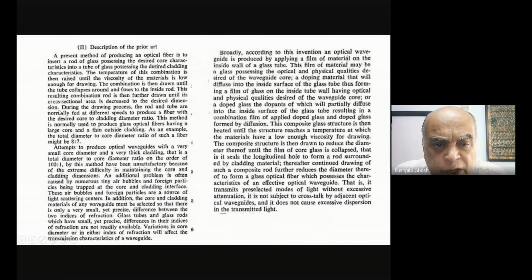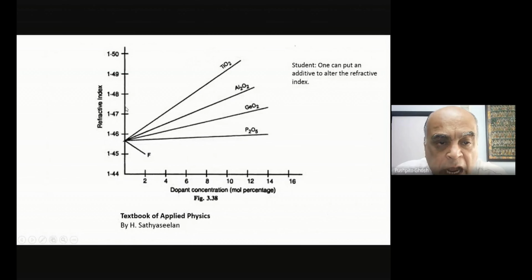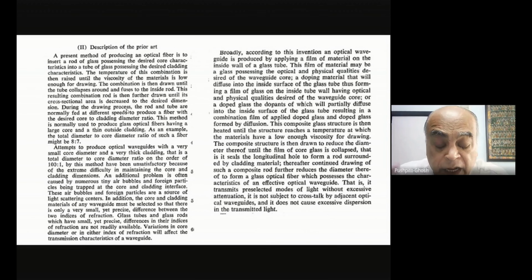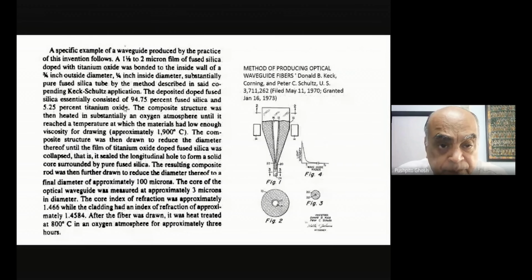And so you can actually go back to this and you'll know what is the difference in the refractive index which they would have achieved between the core and the cladding. The composite structure was then heated in substantially an oxygen atmosphere until it reached a temperature at which the materials had low enough viscosity for drawing. And what is that? It's about 1900 degrees centigrade. So you need special furnaces to reach these kinds of temperatures, like the induction furnaces and those kinds of furnaces.